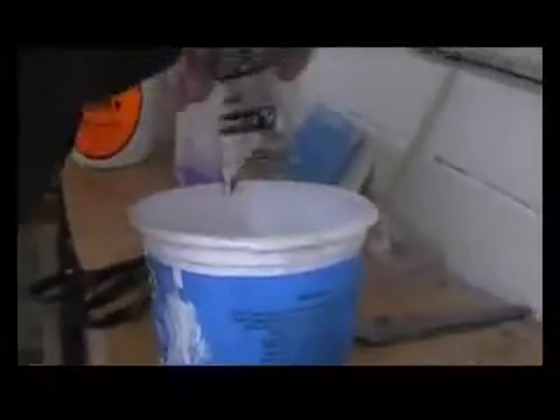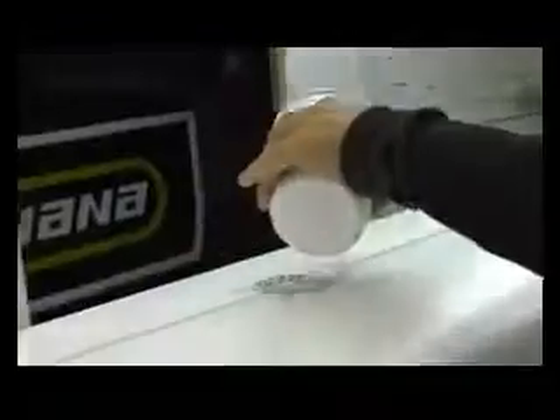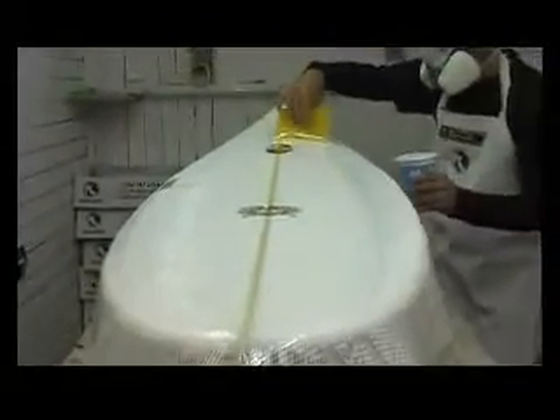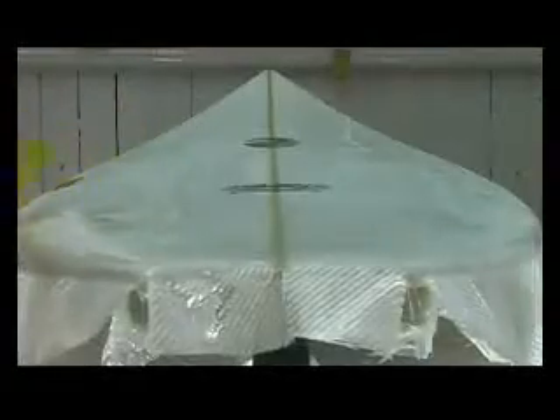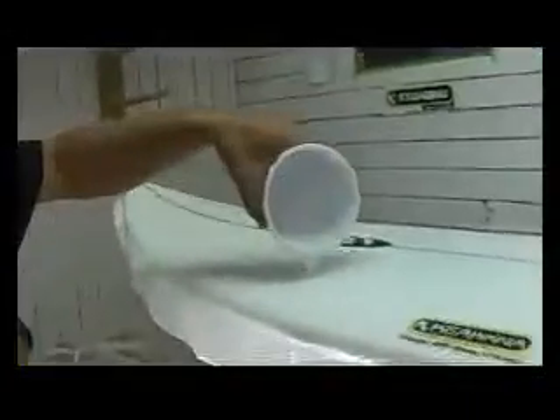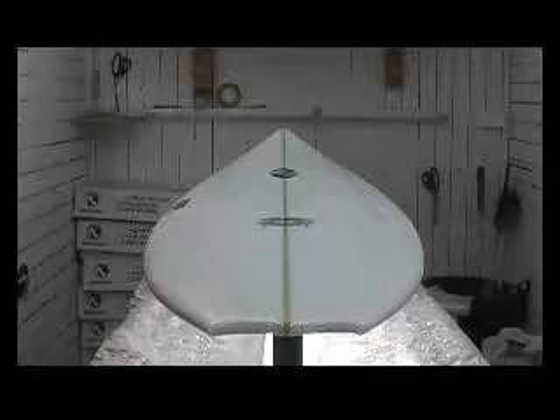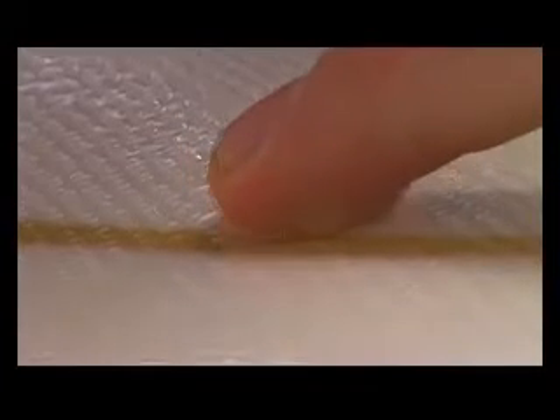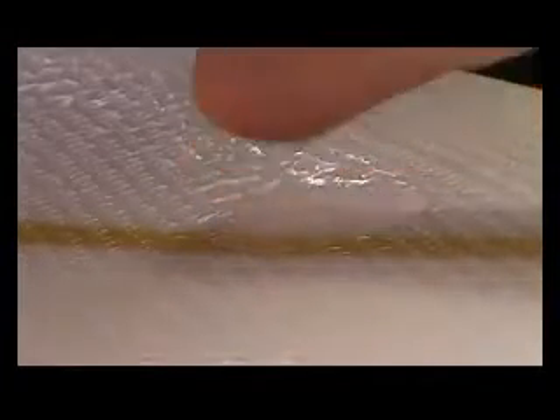Glass the second layer using pot number 4B, glassing deck. Wet the cloths. Apply a bit of pressure with the spatula over the cloth to draw up the excess resin from the first layer. And turn the overlaps in the same way as for the first layer. Carefully remove any excess resin. Let the board rest at room temperature while you wait for the resin to reach its gel point. Test this by using the fingerprint test. At this stage, step number 5, hot coat deck, must be done.